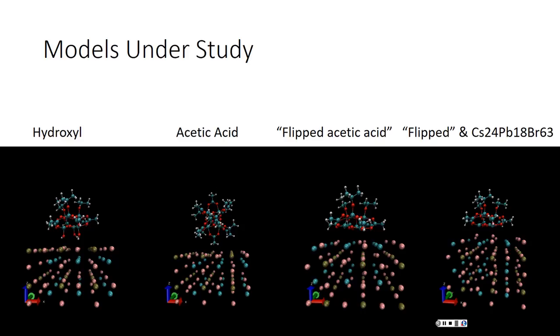So once in your history you were synthesizing solar cells of perovskites. What were the conditions? I guess when I was actually making these, what I would do was anneal the perovskite onto a glass slide. Oh, sorry, actually, first I did the titanium dioxide, and after that settled, then I annealed the perovskite onto there. The method that I was using wouldn't be easy to actually attach any ligands onto the perovskite itself.